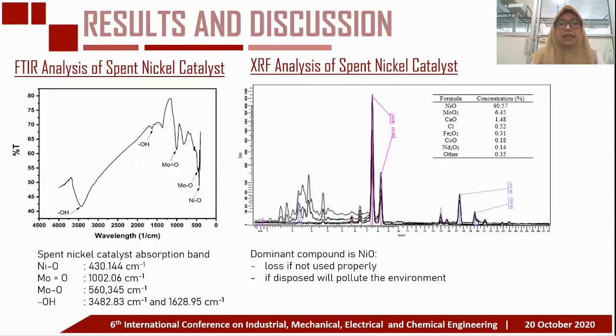Then about results and discussion, for FTIR analysis. First, it is necessary to know the elemental composition in it. FTIR test showed the presence of NiO, MoO, and OH, and then the test was proven by the XRF test, which showed that the most dominant compound in the spent catalyst was NiO, followed by molybdenum trioxide. The high concentration of NiO can prove that if it is not utilized, it will suffer losses, and if it is disposed of, it can pollute the environment.